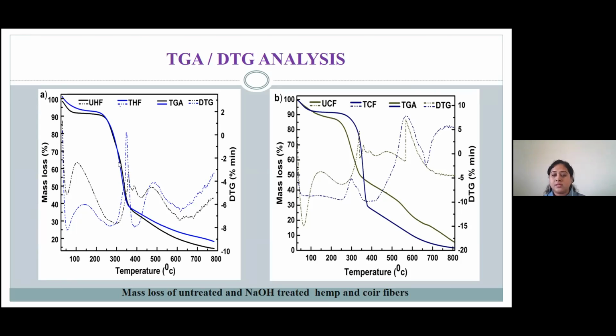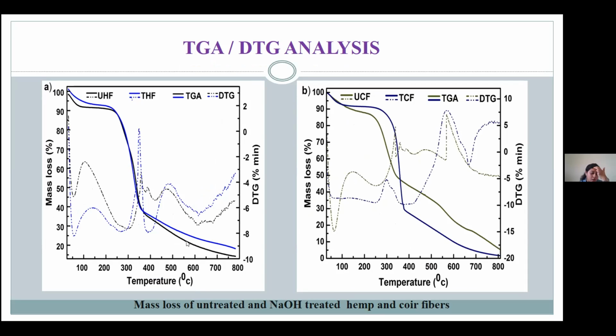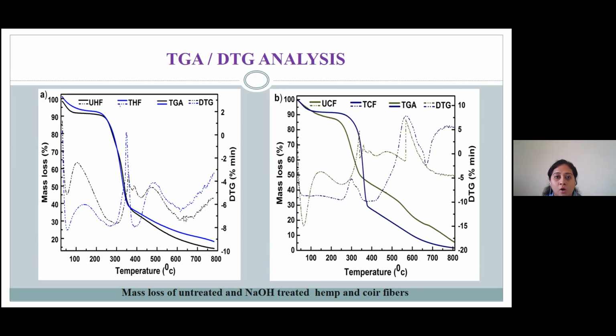Comparing the results with the parent fibers, the position of the bands for both treated fibers are presented here for hemp and coir. For both treated fibers it has changed and shifted towards the right, as you can see in the blue graph. The TGA curves beyond 600 degrees Celsius show minimal losses.